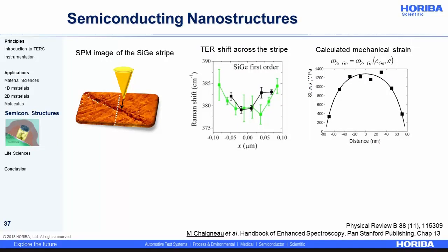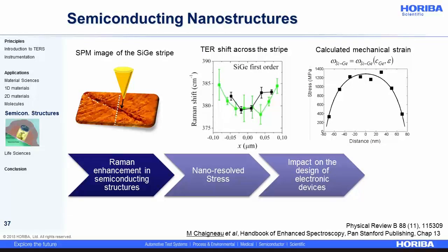And thanks to well-known formulas that can be found in the literature, linking this Raman shift with the local strain in the nanostructure, we can calculate the mechanical stress, which is about 1.2 gigapascal in the center of the stripe and almost vanishes at the border. So the Raman enhancement in semiconducting structures thanks to TERS helps to probe a nanoscale value of the stress. And this stress information would obviously be useful for studying the impact on the design of electronic devices.